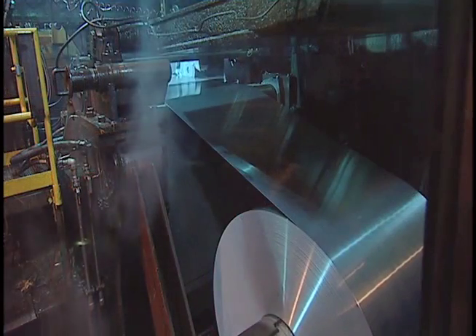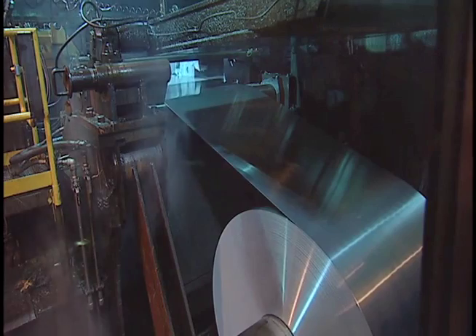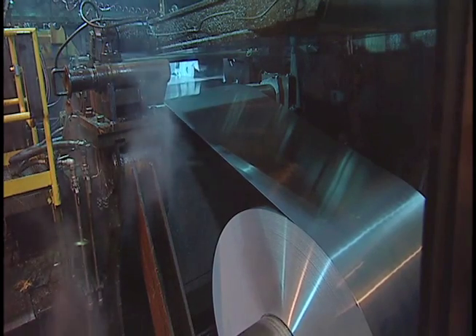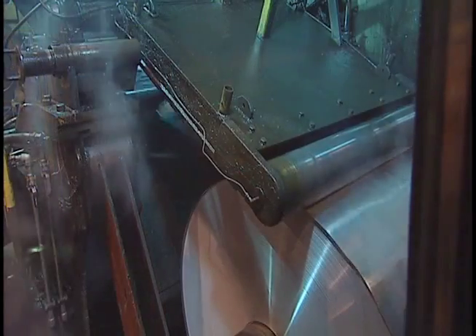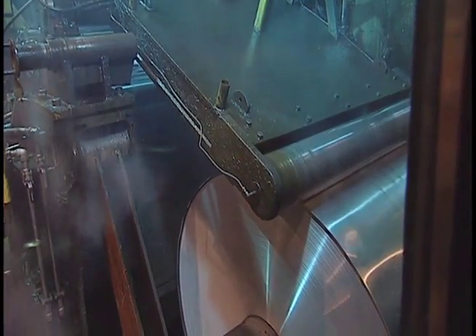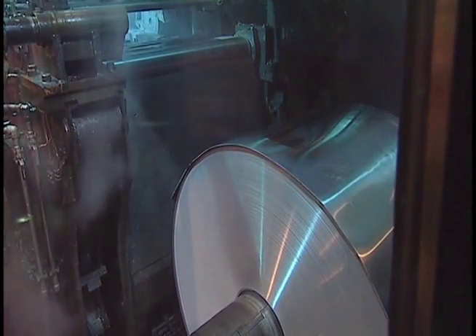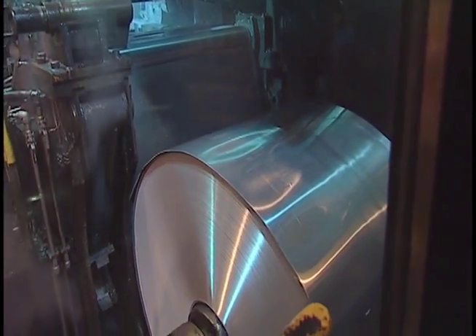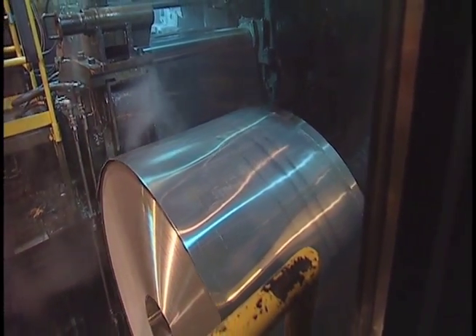The force exerted by the finishing mill's work and backup rolls causes the slab to decrease its thickness to 1/10 of an inch. Roll coolant is also applied to decrease friction and cool the rolls. Can body will take approximately 6 minutes to run through the finishing mill to form a coil, whereas can end will take approximately 8 minutes.